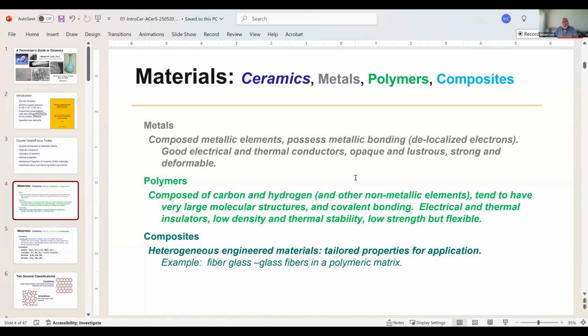Okay. Composites are interesting, and there's a lot more interest in composites in recent years, particularly with emphasis on the design of high-performance materials. These are engineered structures, so their properties are tailored for the application. The best example is fiberglass. Fiberglass is a glass fiber that's embedded in a polymer matrix. In that situation, the glass fiber carries most of the load, but the polymer matrix provides some flexibility. These structures are heterogeneous, and they're highly oriented; in other words, their anisotropic properties are highly dependent upon the orientation of the fibers.